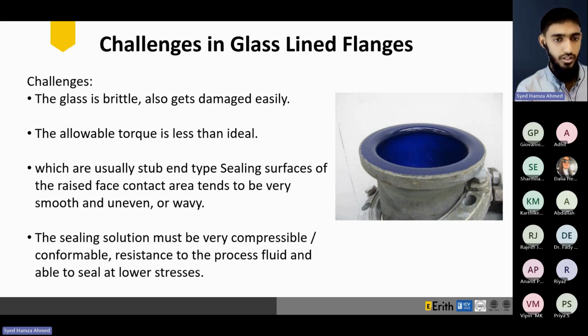Not only is the glass brittle and easily damaged, the allowable torque, while not as low as for the polymer or rubber lined flanges, still tends to be less than ideal. In addition, the sealing surfaces, which are usually stub end, as you can see on the right side in the diagram, the stub end has the slip-on flange.